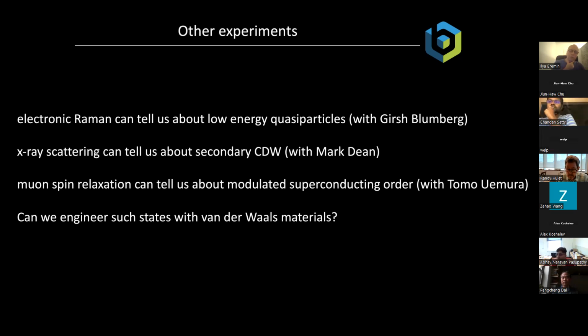And the second short question in the same direction that Pinchenko has asked. When you were showing these nice Smectic directions, that was, however, taken at one particular bias, right, around the coherence peak. So I was wondering what will happen if you slightly go away, or if you go to the negative bias, whether in that case the orientation of the Smectic will change. So, yeah, the orientation does not change.